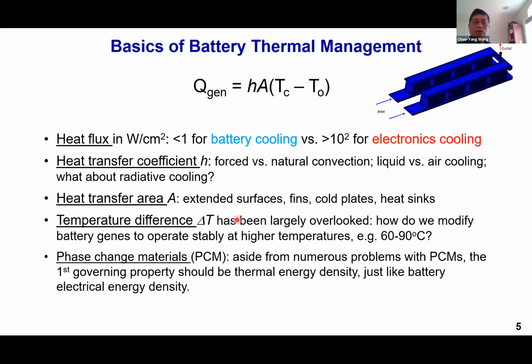One last note that I want to put down here is about phase changing material, because this is something that has also been researched and suggested in the practice of battery thermal management. Aside from numerous problems with PCM, the solid-liquid phase transformation, the leakage problem and all that, for phase changing material I would look at the most important parameter, and that is energy density, because phase changing material essentially is thermal energy storage. It's very much like a battery as electric energy storage, right? So we should look at the thermal energy density.